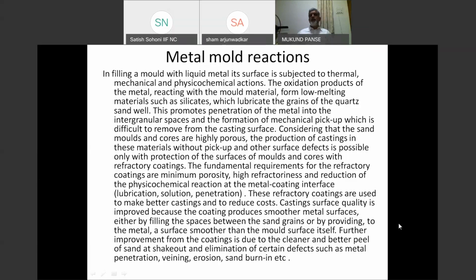To avoid this, you will try to have a coating of refractory material which will close the pores. The refractory material has substantially higher refractoriness. It is less reactive with the metal, and you try to get a better surface finish. This is the basic requirement of a coating. So it should be a barrier between the metal and mold. It should have better thermal characteristics, high refractoriness, non-reactiveness, and very small size, so that you get a better surface finish.